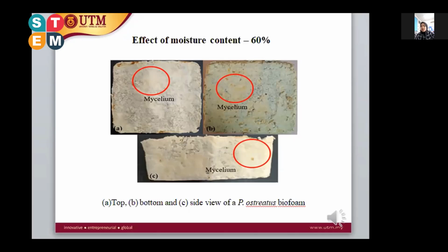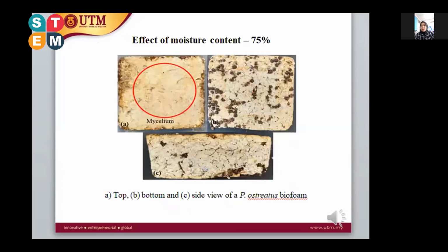Here is the effect of the moisture content of 60%. A high concentration of mycelium will be observed on the top of the substrate after 10 days. The mycelium grows well on top of the substrate because the gradient in oxygen concentration on top is more than the bottom, when the air enters the lid of the containers at the top. So for the 75% moisture content, we can see that there is no colonization of mycelium that can be clearly observed at the bottom and the side of the biofoam with 75% of the moisture content.